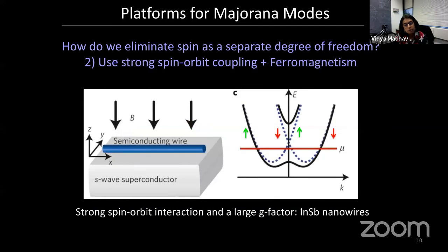The other way to eliminate spin as a separate degree of freedom is by engineering the band structure of the system. So here's an engineered system. Let's say you have a semiconductor with very, very strong spin-orbit coupling. Then the regular bands, which are usually spin degenerate, get split in this way by spin-orbit coupling. Now let's just look at the dotted lines. That's what Rashba does to you. It splits the bands in this fashion.